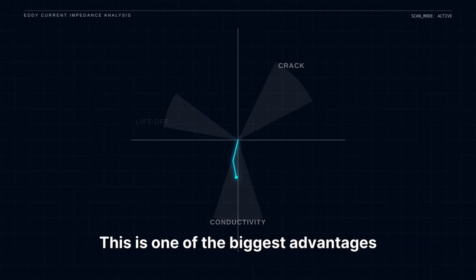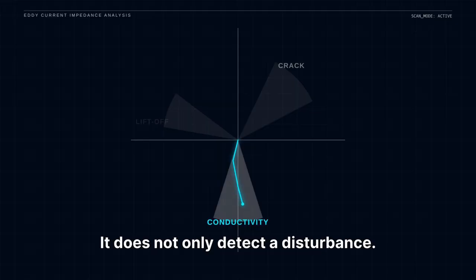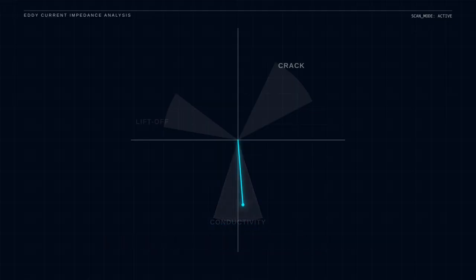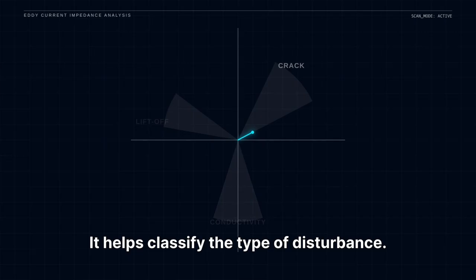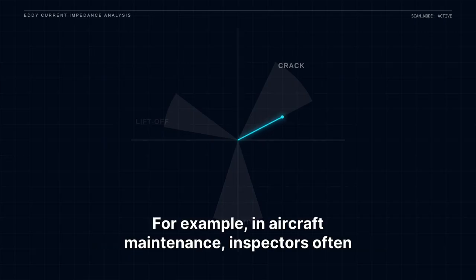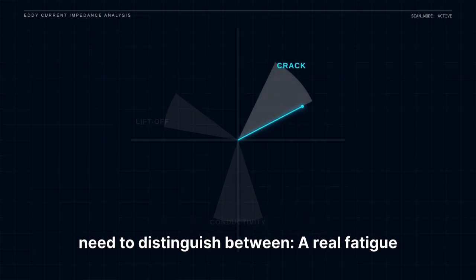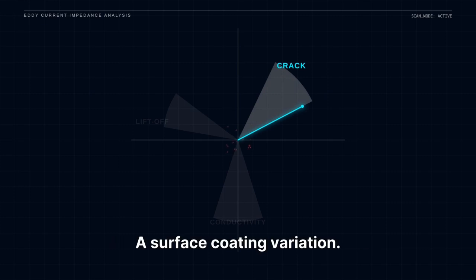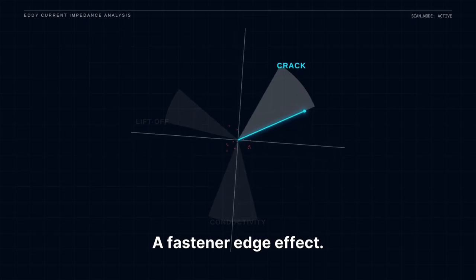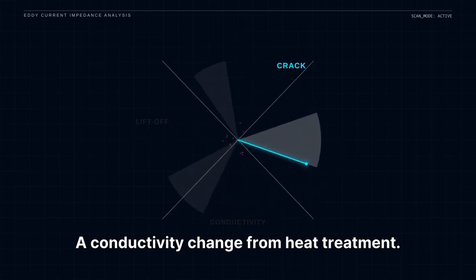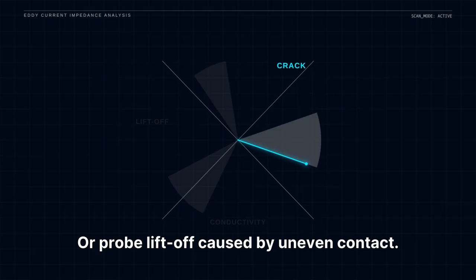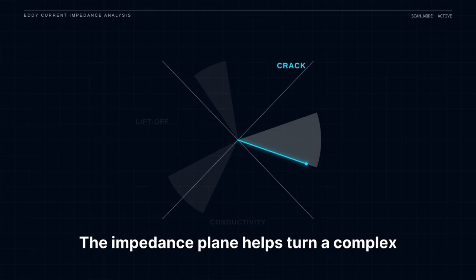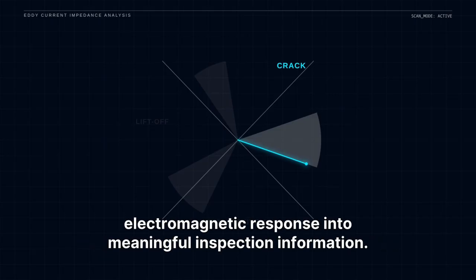This is one of the biggest advantages of eddy current testing. It does not only detect a disturbance, it helps classify the type of disturbance. For example, in aircraft maintenance, inspectors often need to distinguish between a real fatigue crack, a scratch, a surface coating variation, a fastener edge effect, a conductivity change from heat treatment, or probe liftoff caused by uneven contact. The impedance plane helps turn a complex electromagnetic response into meaningful inspection information.